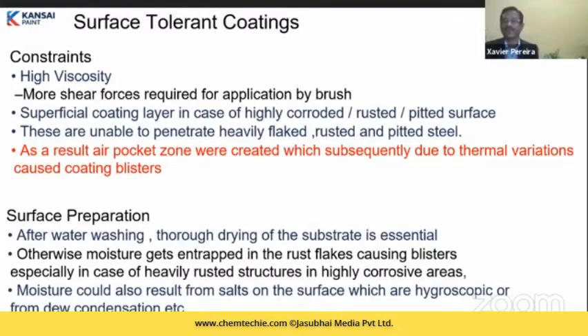And very often, if you remove a rusted scale, you can find a tinge of moisture at the pit of the rust flake, and that has been seen there, right? And moisture also could be because of the heavy laden salty atmosphere, which is hygroscopic, and during the condensation there is a lot of absorption that takes place. So this water was there. So two observations: one, the coating as a surface tolerant epoxy would cover only the superficial covering. It would not penetrate inside. Second, the water which is used for water washing of the substrate remained inside.